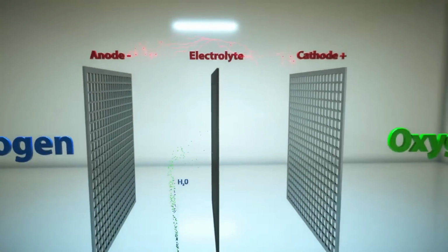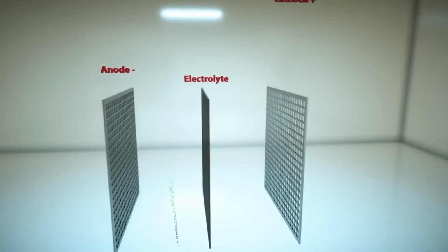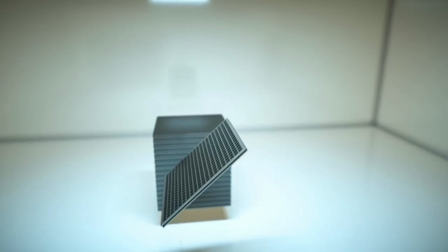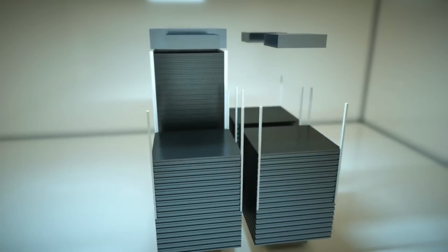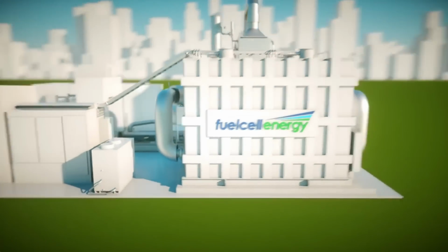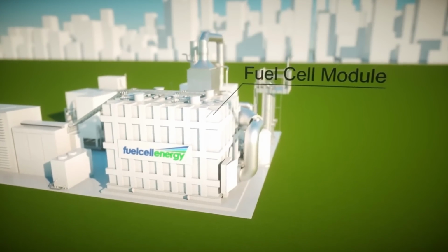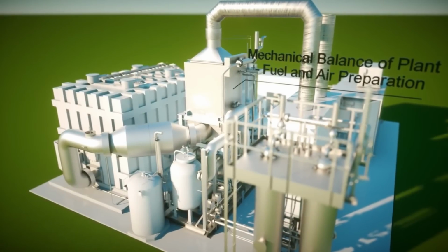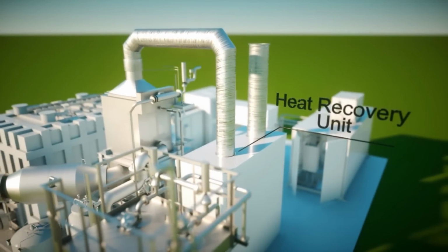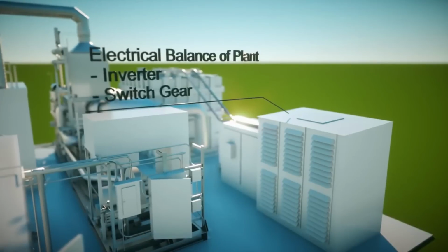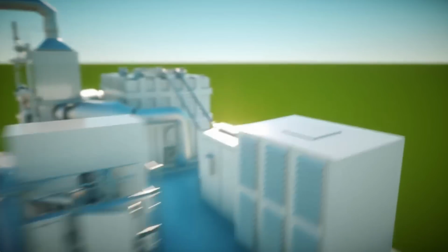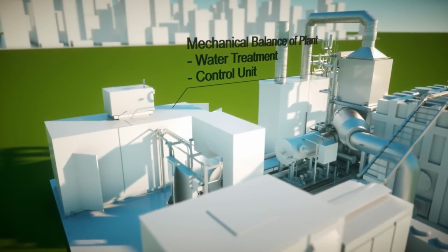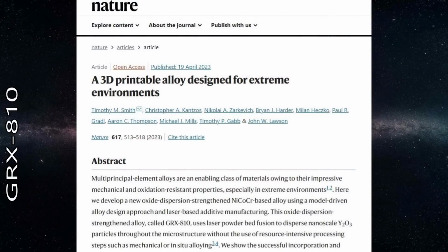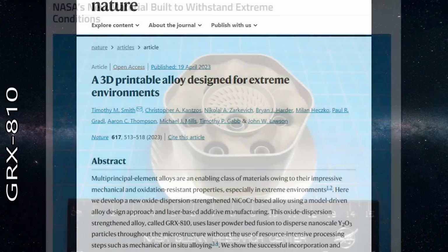Additionally, Inconel alloys possess favorable mechanical properties, such as high tensile strength and good thermal stability, which are essential for supporting the structural integrity of MCFC components. These alloys exhibit dimensional stability under the thermal cycling experienced during startup, shutdown, and load cycling of the fuel cell. But while Inconel has been amazingly effective as a high-temperature corrosion-resistant material so far, even better alloys are being developed thanks to advanced technologies. One of these innovative alloys invented by NASA is GRX-810.